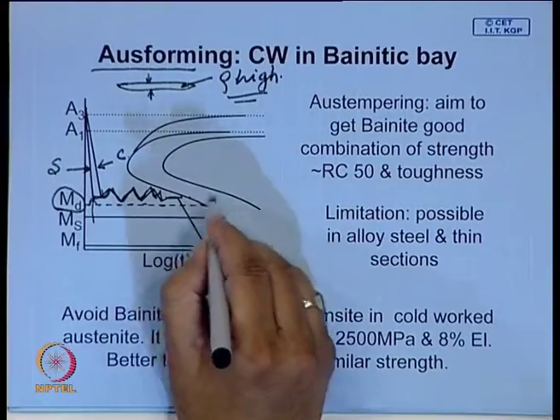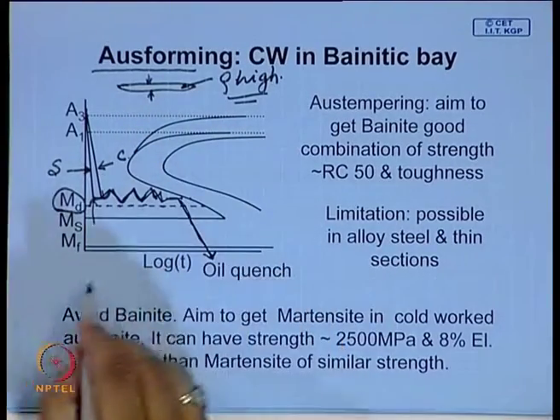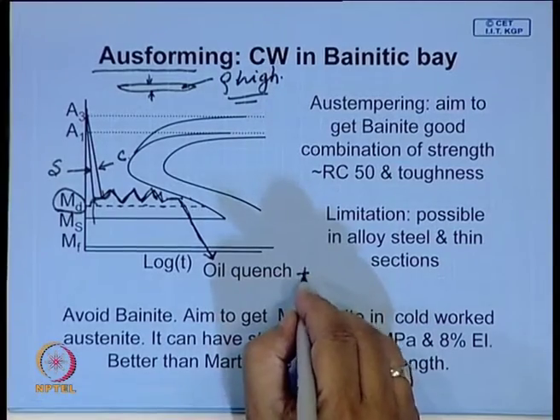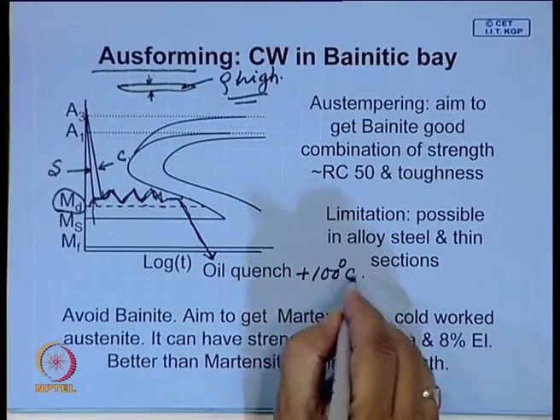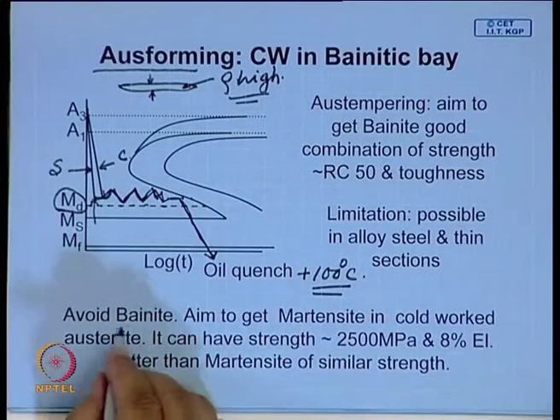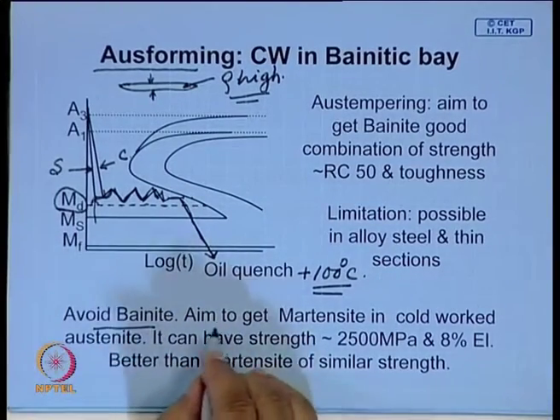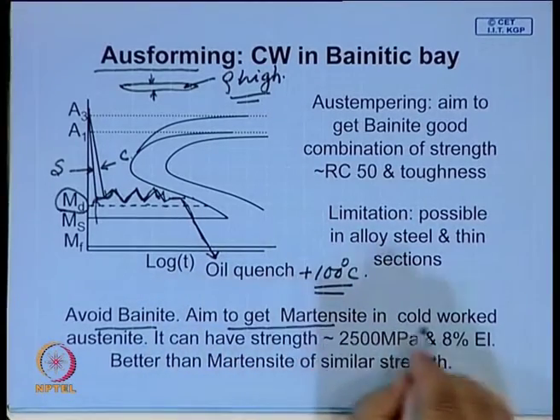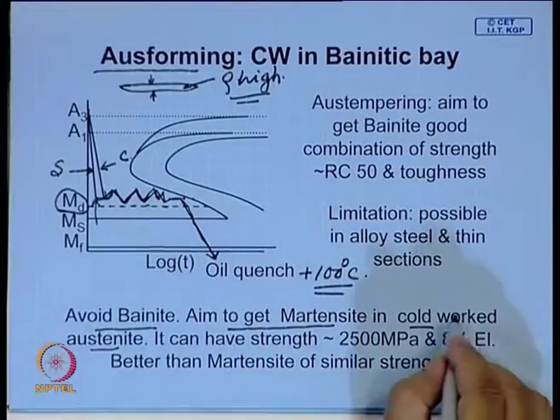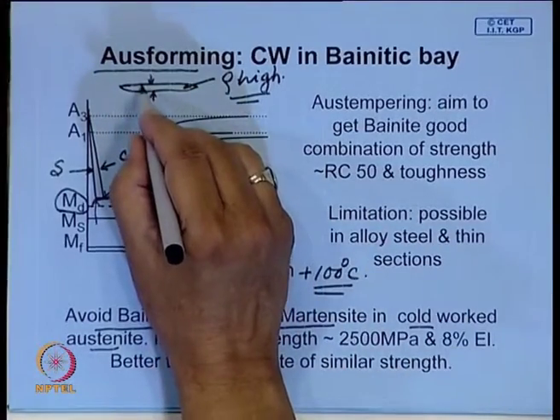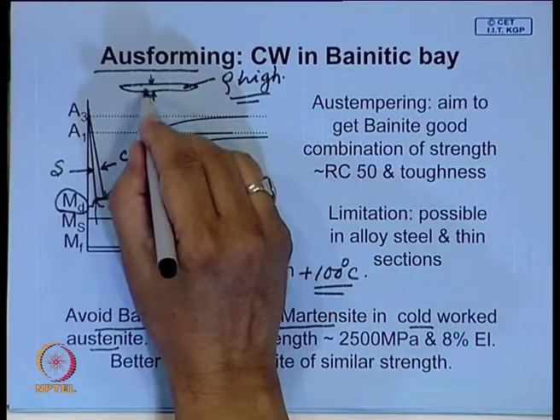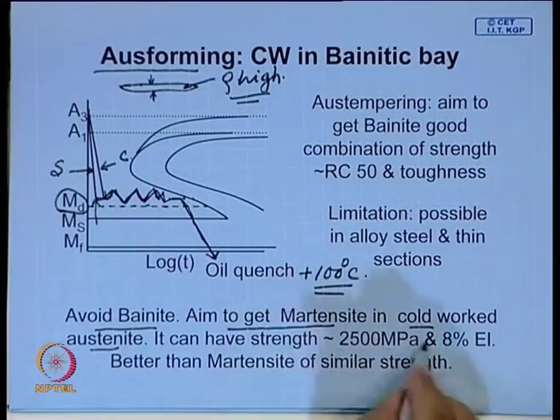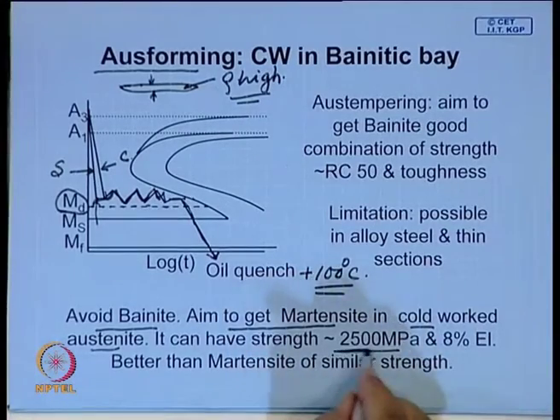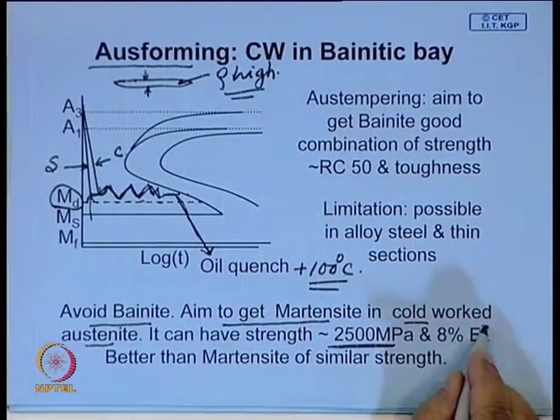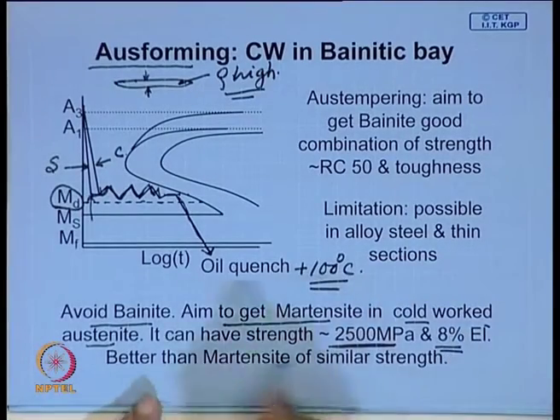So, do this, give cold working above MD, and after the cold working is over and before this bainite starts forming, you quench the steel, and after this it is necessary to give some tempering, maybe 100 degrees centigrade, you temper to relieve internal stresses. But the key thing is you avoid bainite and you get martensite in cold worked austenite. So, austenite is also very hard, within that also you get finer, much finer martensite, and this dislocation density will be much higher, and here you can attain a quite high strength level, yet you will have sufficient ductility, which is not possible in martensite of similar strength.